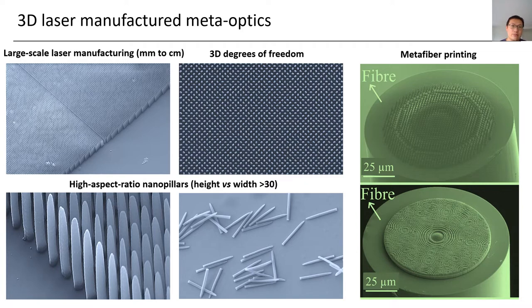I will introduce 3D laser manufactured meta-optics, where we can use the 3D direct laser writing technology to print 3D meta-optics, 3D metasurfaces, which means that this metasurface doesn't have these restrictions on the single height. In general, based on this planar lithography approach, we end up with metasurfaces with a single height because you have to go through the etching process in general or through some film deposition that has a single height, where you lose this degree of freedom in height. Well, if we use the 3D laser printing technology, we can just unleash this third degree of freedom in height, which can achieve better optical responses, as I can show later.